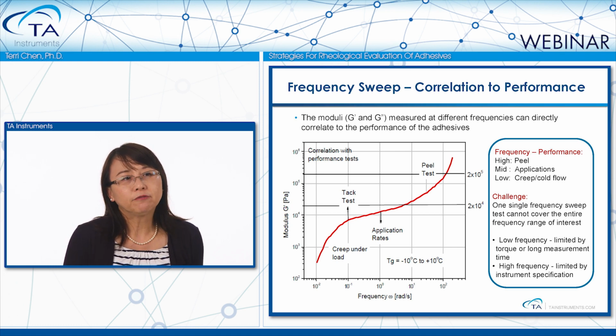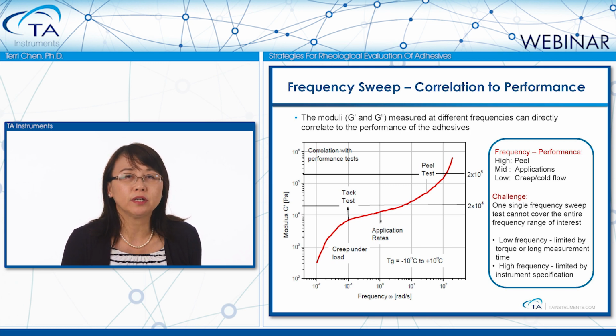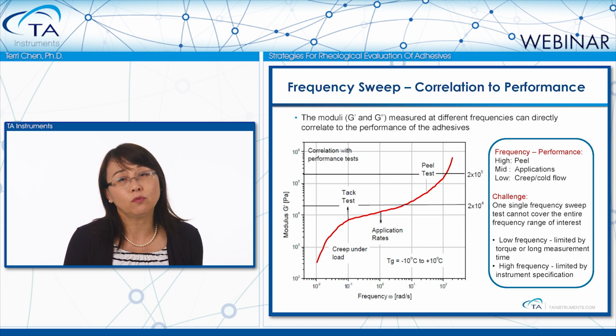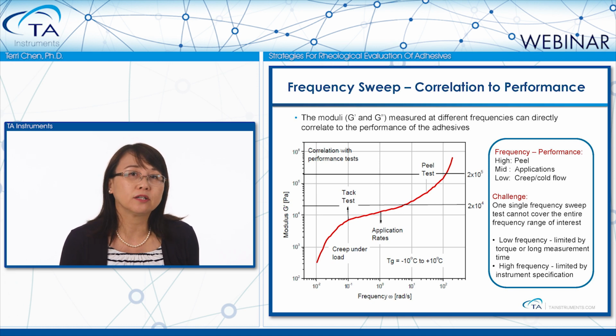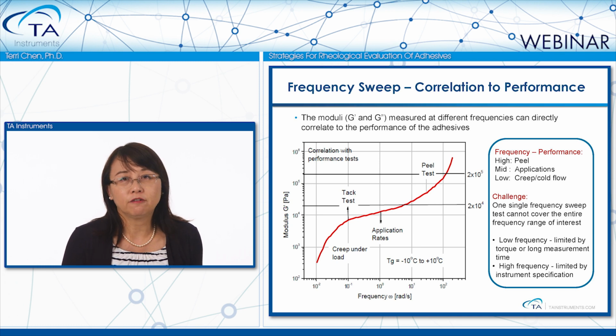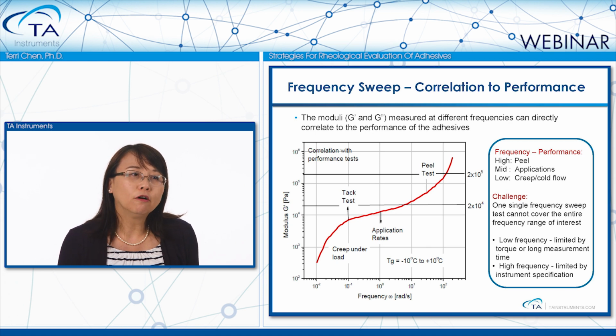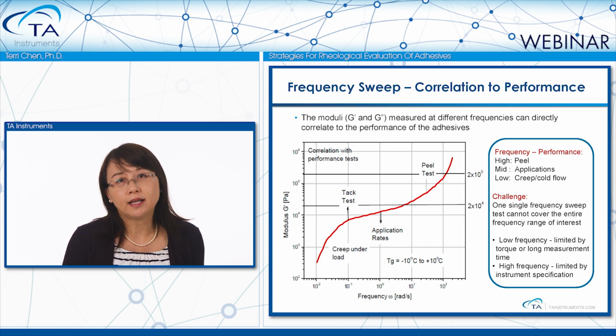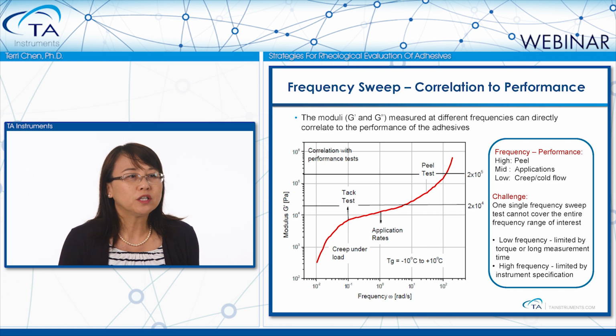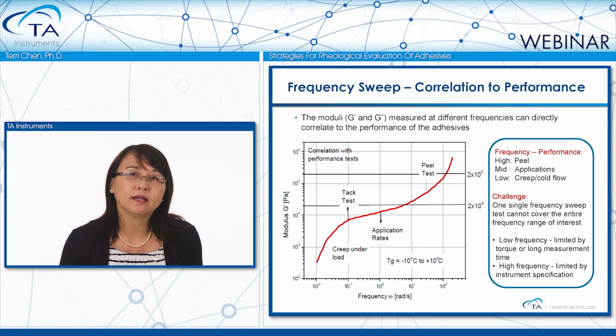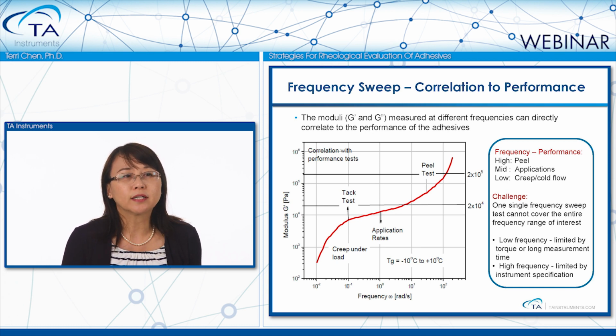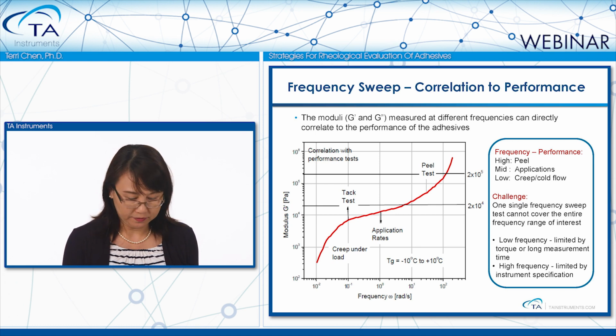However, the maximum frequency a rotational rheometer can reach in one single test is only 100 Hz, which is 628 radians per second. This may not be high enough to mimic a certain high shear situation. Also, low-frequency data may require days or years to collect, which makes the measurement practically impossible. In this case, a time-temperature superposition technique can be explored to extend this measurement frequency range.